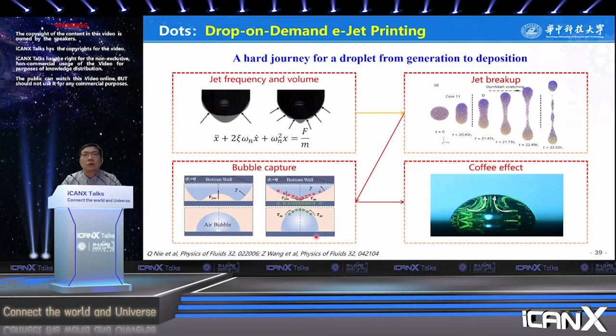It's also harmful for printing. When the electrical field is applied, the charge will gather at the two ends of the jet. When the charging jet is close to the substrate, the Taylor cone will form at the bottom end. It's helpful to drive the air bubble out of the center.